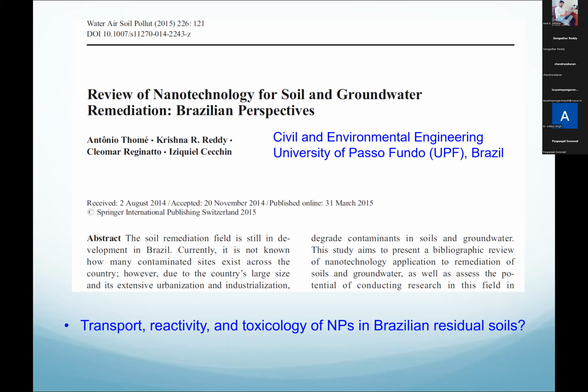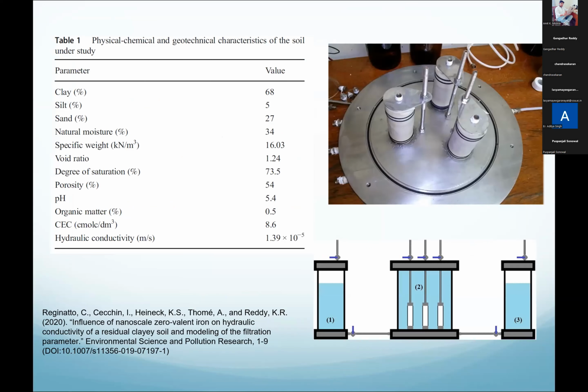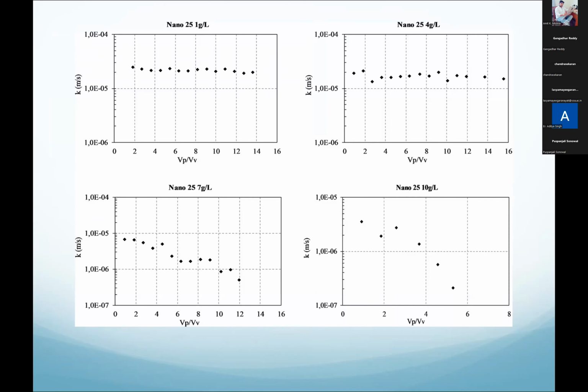They have a huge unsaturated soil zone, and you want to use these nano iron particles to treat the soils, right? So how can we use the local ecological organic stabilizers? So this is the permeability test. First of all, you need to look at the soil that you get. And they were able to have this traction machine where you can put 3 samples together and test it. You're flushing this nano iron solution through the samples and then seeing how much is coming out individually from each of them. And then you look at the permeabilities.